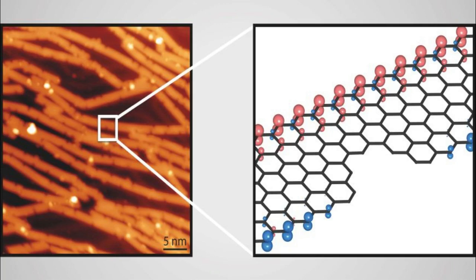Again, using scanning tunneling and atomic force microscopies, the researchers first identified the presence of ubiquitous carbon vacancy defects located at the edges of the nanoribbons and then resolved their atomic structure. Their results indicate that each vacancy comprises a missing m-xylene unit, that is another bite defect, which, as with those seen in AGNRs, comes from the scission of the C-C bond that occurs during the cyclodehydrogenation process of the reaction. Researchers estimate the density of bite defects in the 6ZGNRs to be larger than that of the equivalent defects in bottom-up AGNRs.